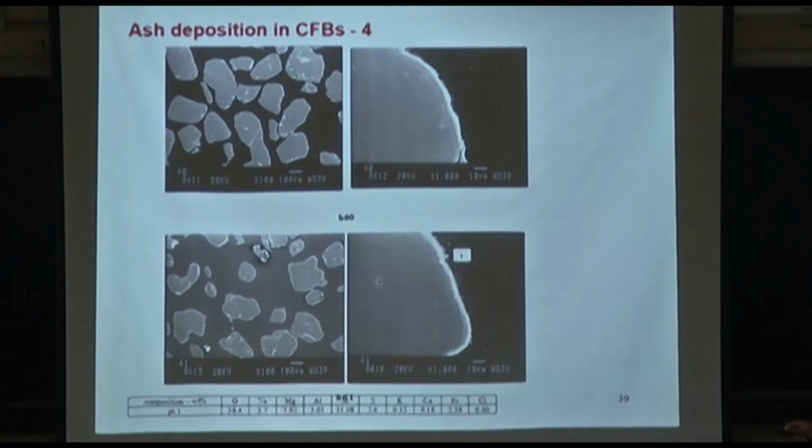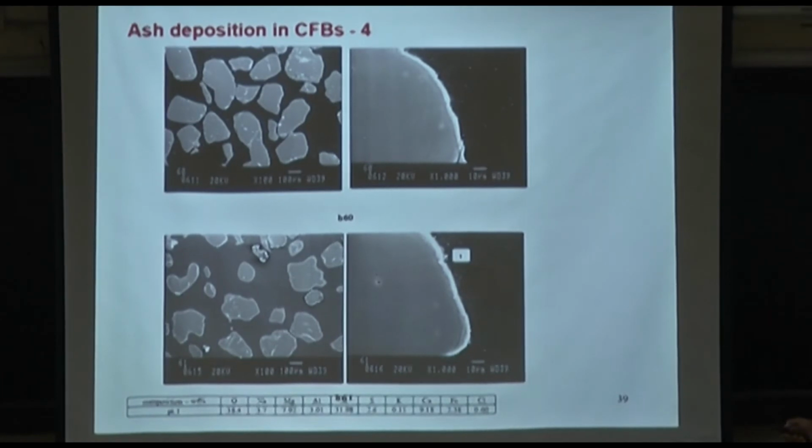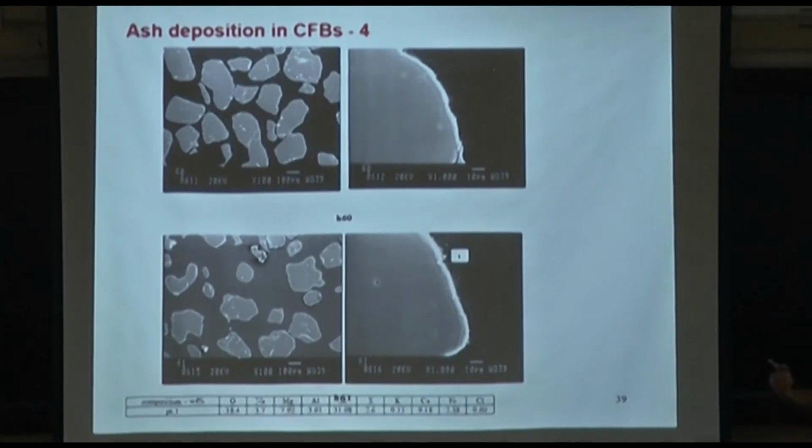We did the EDX. So when we looked at the individual particles, not exactly those ones I am showing in here, other particles from the same agglomerates, same batch of agglomerates. So this is the pristine actual sand particles, and over that there is a thin film of the gluey sticky substances forming.